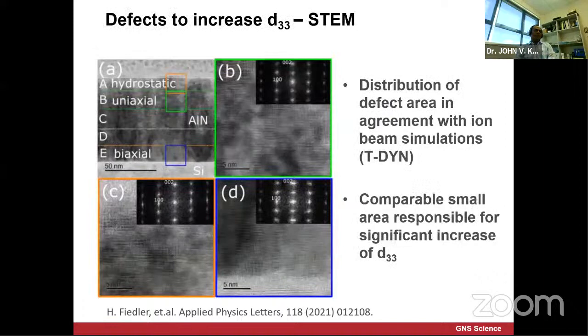Then when we look at the defects in STEM images, as I said, you can easily look at the distribution of defect area. With ion beam simulations before, you can now compare with the actual measurement we do. So the STEM images show hydrostatic, uniaxial and biaxial cross-section films. This is from the aluminum nitride. So these are the bright field STEM images of, let's say, sample A, implanted with 10^15, which is the number A, giving you where the aluminum nitride uniaxial and biaxial stress is happening if you look closer at it.